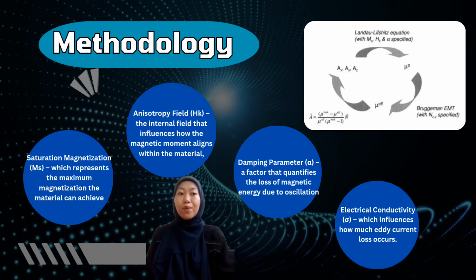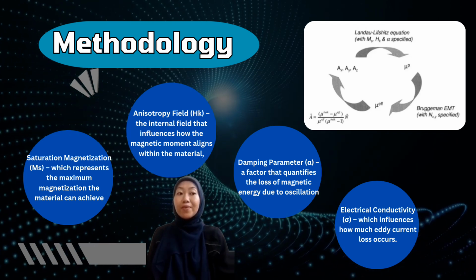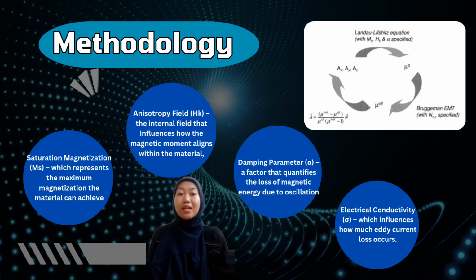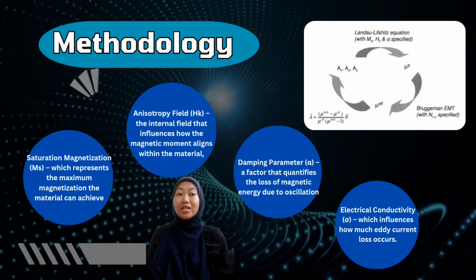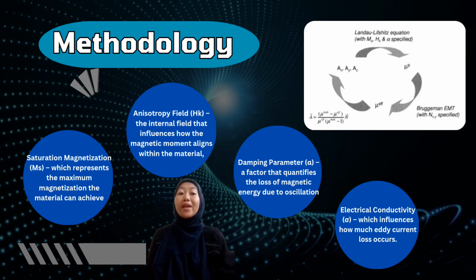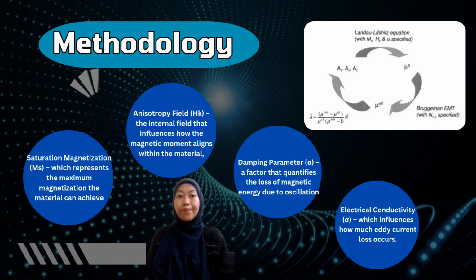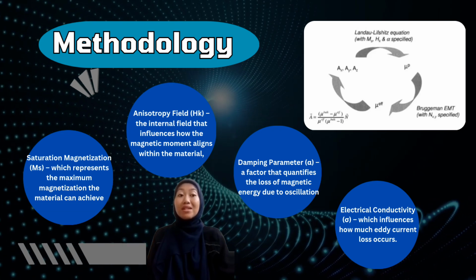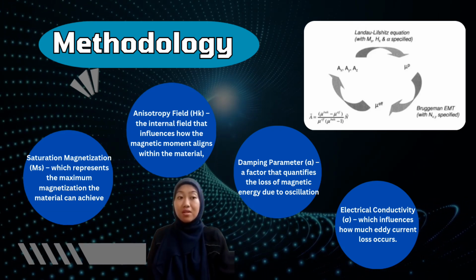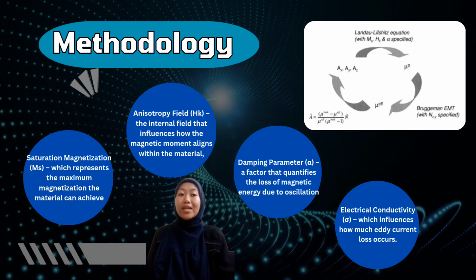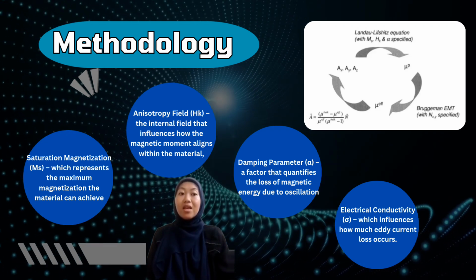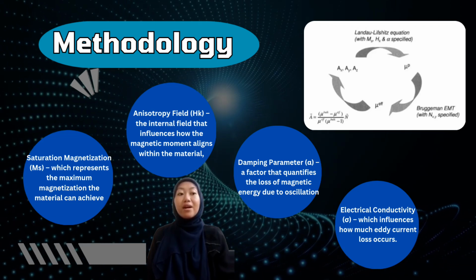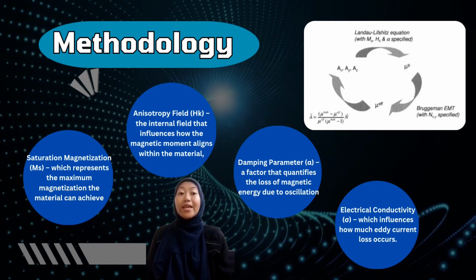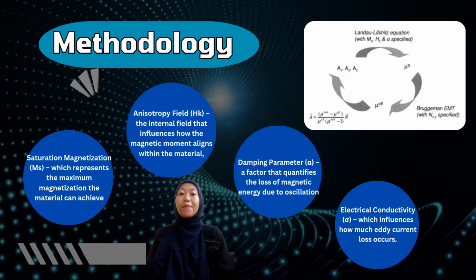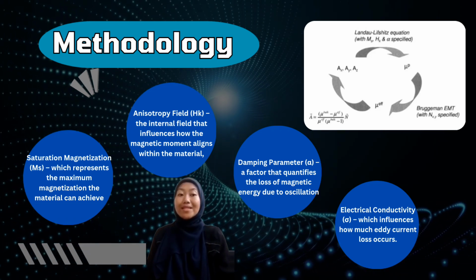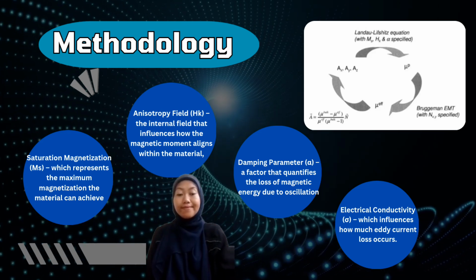These parameters are used within the framework of effective medium theory (EMT), specifically the Bruggeman and Maxwell-Garnett models, to estimate the overall magnetic response of the composite system. The model is applied to scenarios involving isolated particles and those in contact to simulate different packing densities. Key equations like the Landau-Lifshitz equations and Kittel's formula are used to compute permeability and FMR frequency across different configurations.